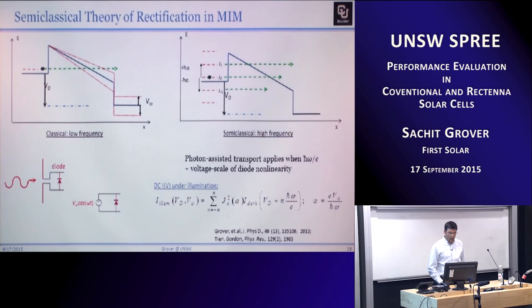What I will go into a little bit of depth is to try and explain what is the mechanism of rectification using this diode when we are looking at really high frequencies. So let's start with a classical regime, low frequency. And well, how do we define classical? Well, low frequency would be where the AC voltage, the V omega cosine omega t that is applied across the diode, the V omega is much smaller than the scale of the nonlinearity in the device. So, for example, these barriers are in the range of a few tenths of an eV, and the V omega is in the range of a millivolt. That would be a small classical low frequency regime.